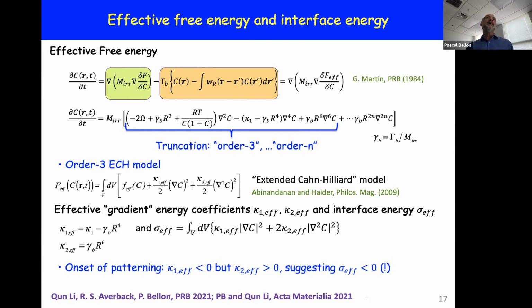But in phase field modeling, it is difficult to deal with these non-local terms, as probably you know too well. Yes. And so what we decided to try is to see whether we can replace this compact non-local term with maybe more terms, but they're all local. And this is what happens when we went from the first line to the second line. So here we replaced this convolution product. It's neat and compact, but it'd be difficult to handle with the phase field model. It'd be easy to do that in Fourier, in reciprocal space, right? Yes.